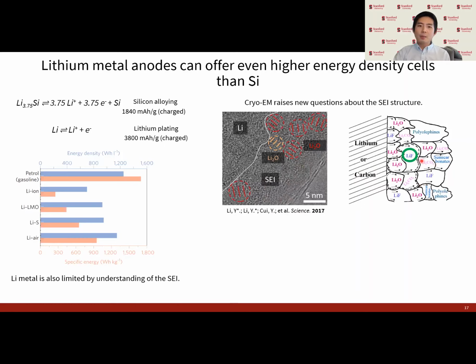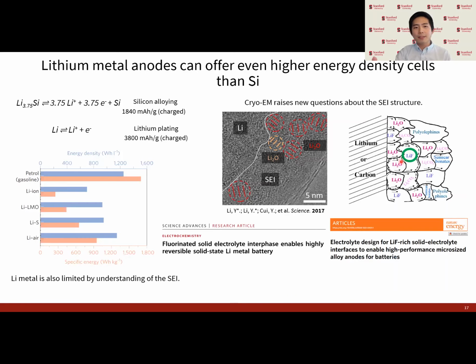But one missing component in the SEI is the lithium fluoride component. And this is important to understand, even though it's just one component in the SEI, because in the literature, it's widely believed that this lithium fluoride is critical to the battery cycling stability. And a lot of high performance anode chemistries rely on these purported fluorinated SEIs. So a significant knowledge gap is now opened in the field, which is where is the lithium fluoride in the SEI?